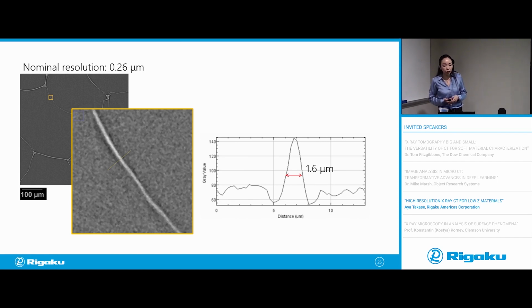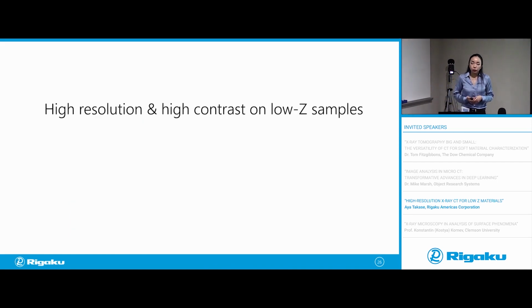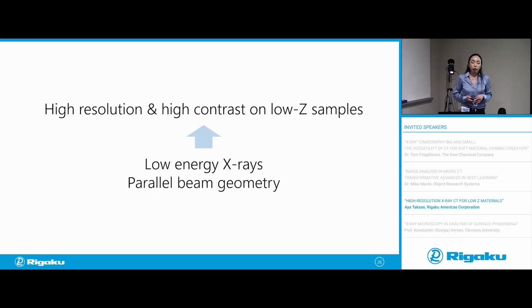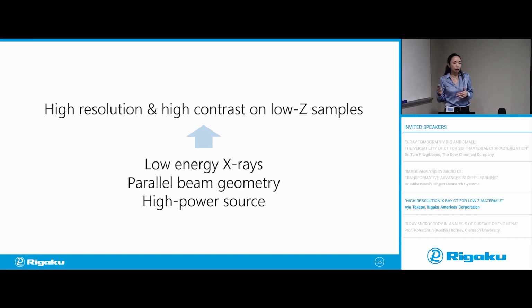So to summarize, if you want to do high resolution and high contrast imaging on low-Z materials or samples, you want to use low energy X-rays. And probably you want to use something other than tungsten to do this. And the parallel beam geometry would be the ideal setup to use for high resolution. And this part I haven't mentioned yet, but you are going to need a pretty high power X-ray source to use low energy and the parallel beam at the same time. And again, in the introduction talk after lunch, I will get more into it.